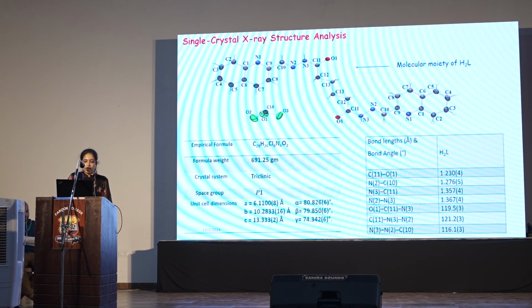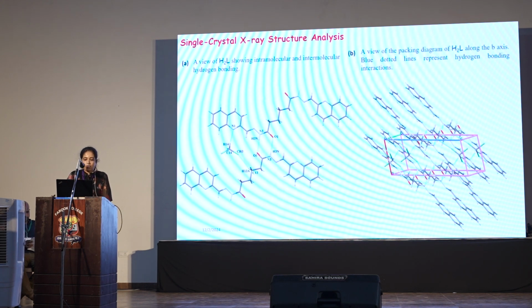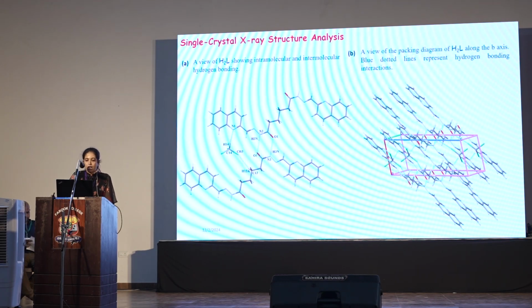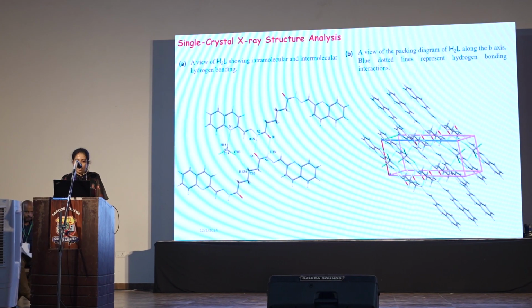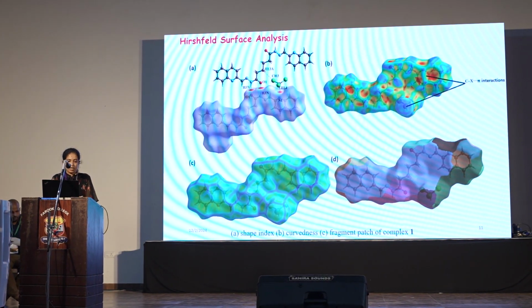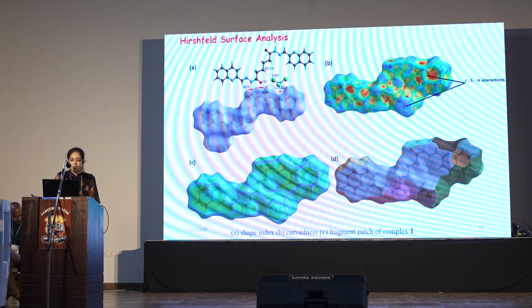The structure of the ligand was established using single crystal X-ray analysis, which shows that the ligand crystallizes in triclinic crystal system with P-1 space group. The table shows the selected bond lengths and bond angles of the ligand. Figure A shows the various intermolecular and intramolecular hydrogen bonding interactions, while B shows the unit cell packing diagram of the ligand along the b-axis. Then we performed Hirshfeld surface analysis to find the intermolecular interactions.